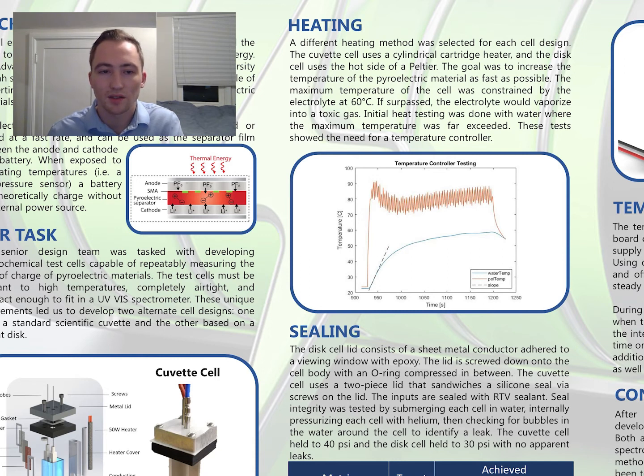Without these limits, and still in the confines of the small cuvette cell, we were able to reach a heat rate of 3.86 degrees C per second. With these constraints added, heat rate results were 0.8 degrees C per second for the cuvette cell and 0.67 degrees C per second for the disk cell. Maximum temperature values were on target at 58 degrees for the disk cell and 52 degrees for the cuvette cell.